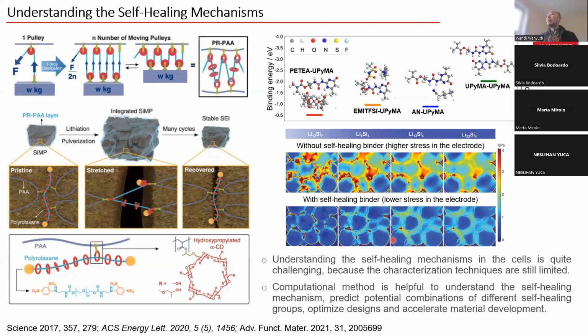Up to now, the characterization techniques are still limited, but in many papers, different self-healing mechanisms have been presented, such as in this literature. They combine PAA binders with polyrotaxanes, and they propose a self-healing mechanism, the pulley concept. The more pulleys we have, the less force we need to retain the initial structure of the silicon electrodes, which is a very interesting concept. But unfortunately, it is difficult to prove this mechanism.